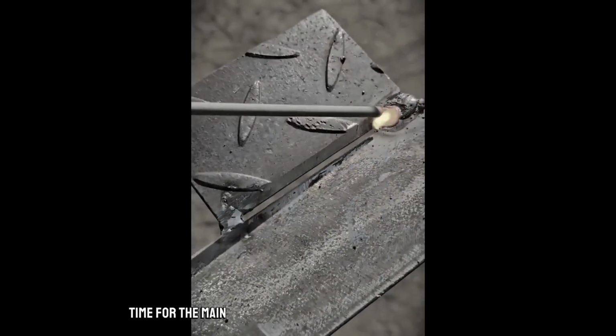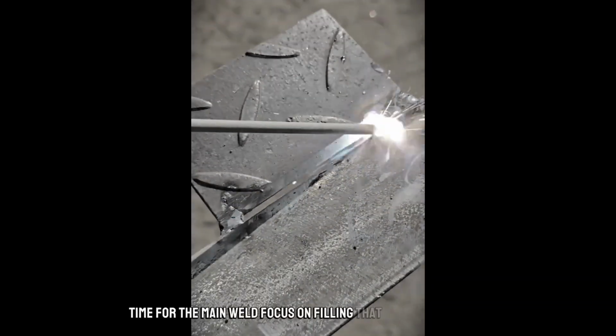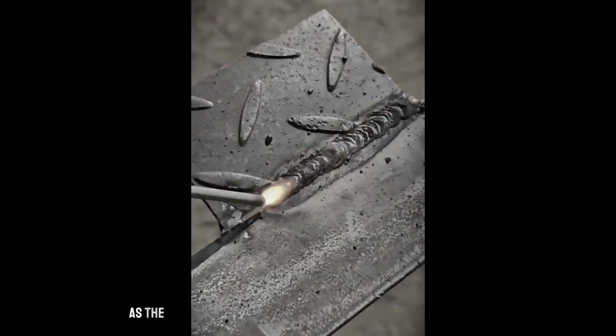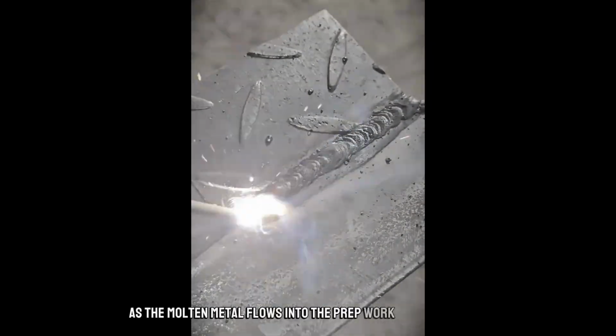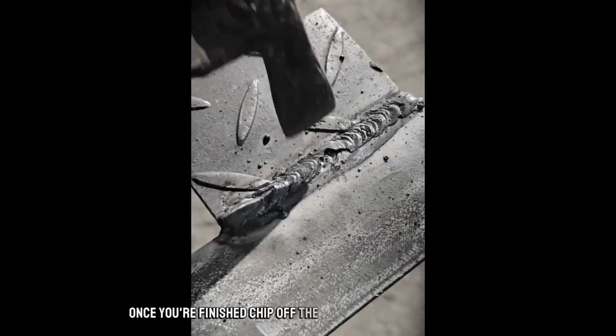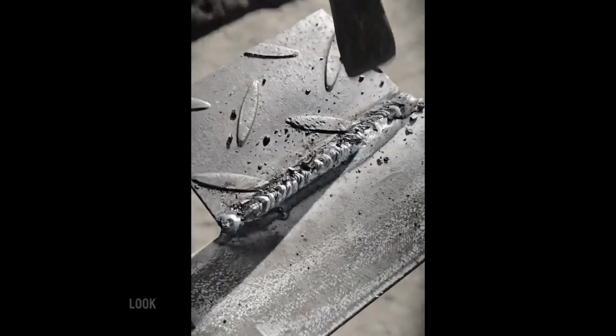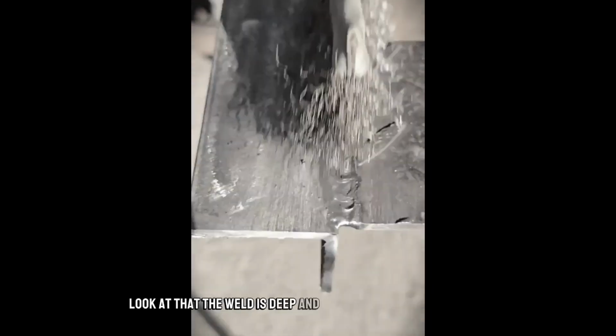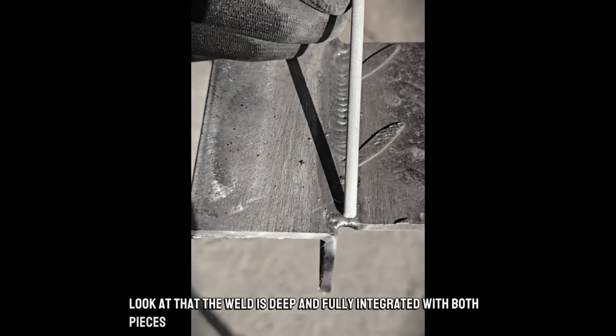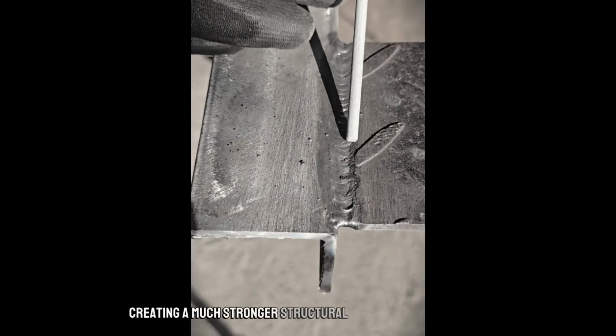Time for the main weld. Focus on filling that groove evenly. You'll notice the arc is much more stable as the molten metal flows into the prep work. Once you're finished, chip off the slag and give it a brush. Look at that! The weld is deep and fully integrated with both pieces, creating a much stronger structural bond.